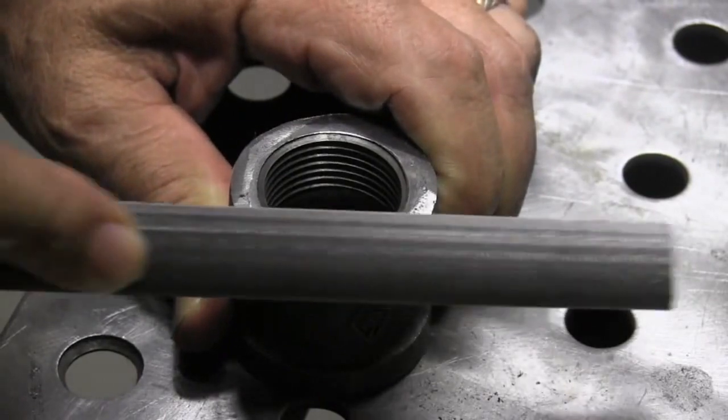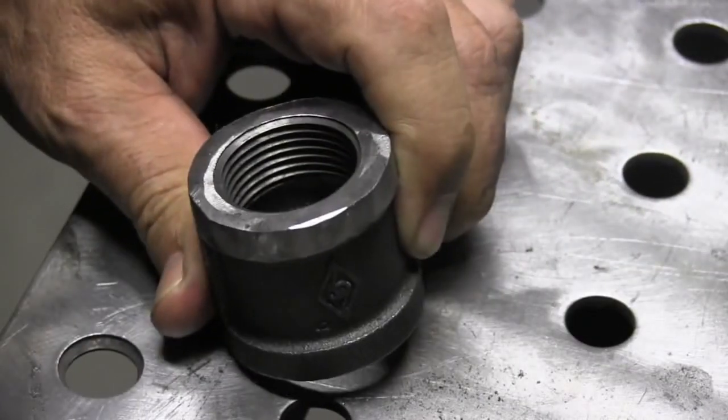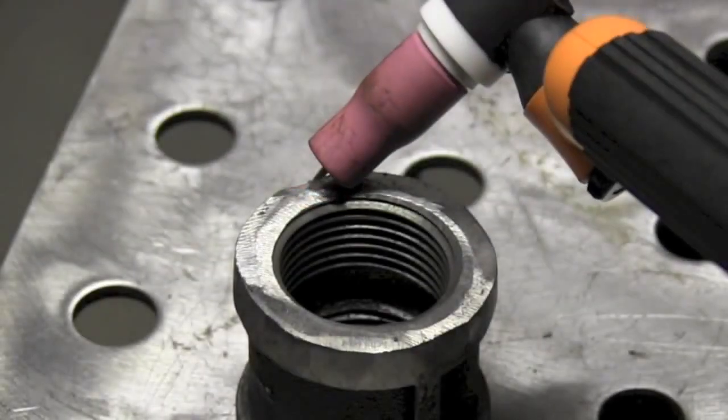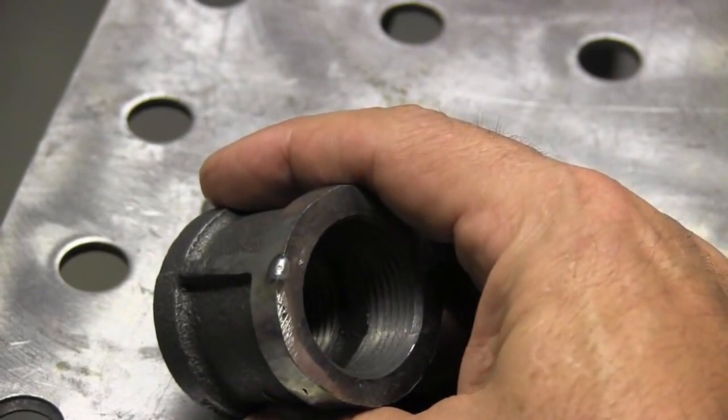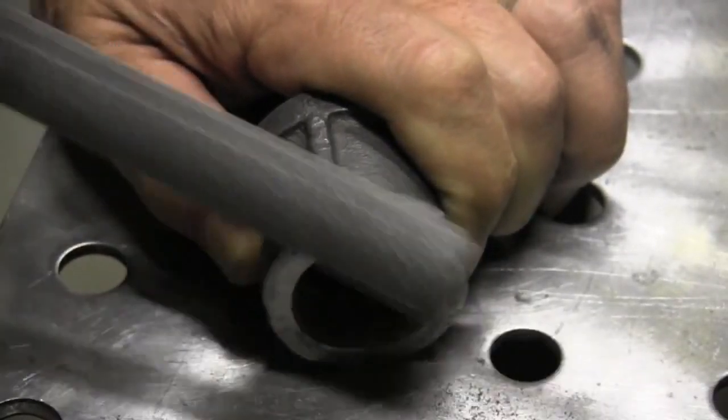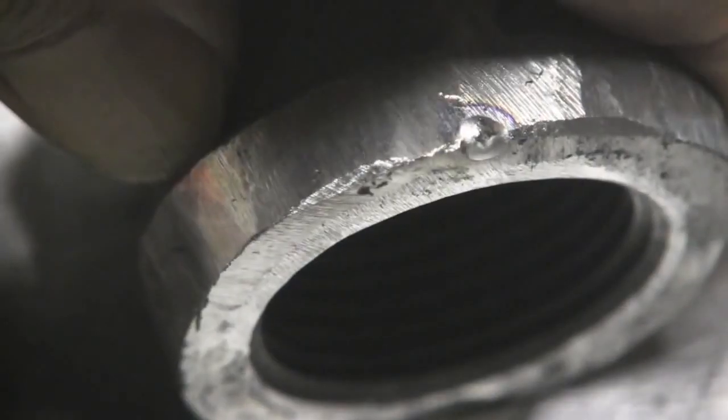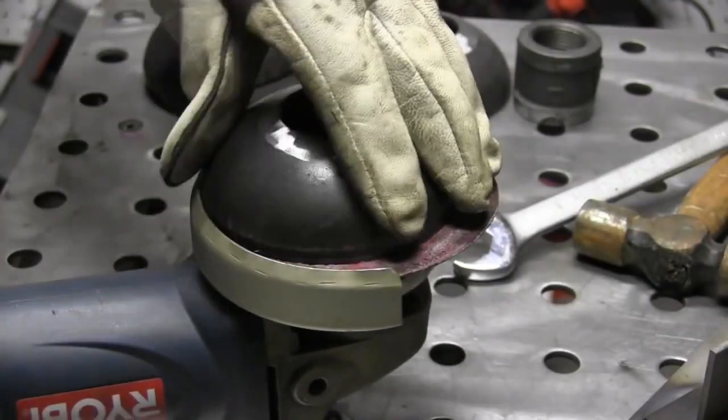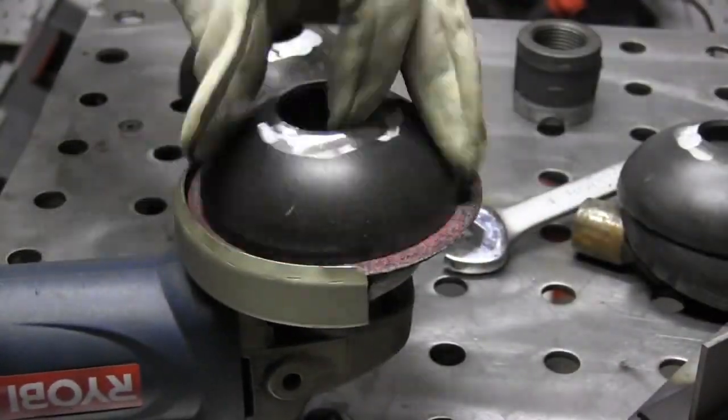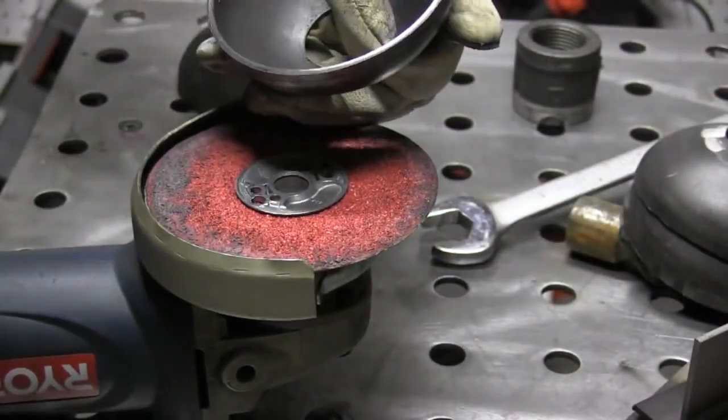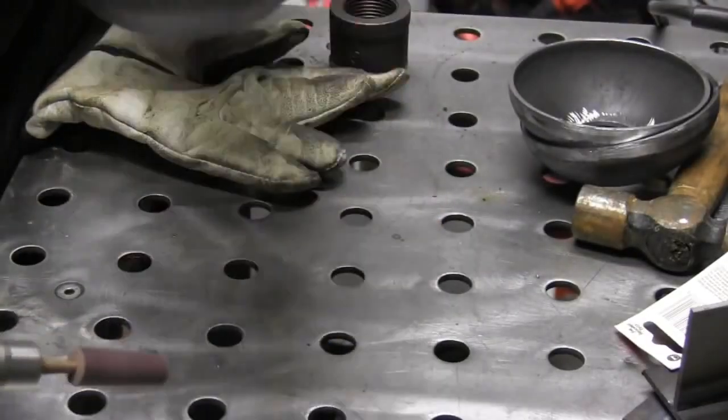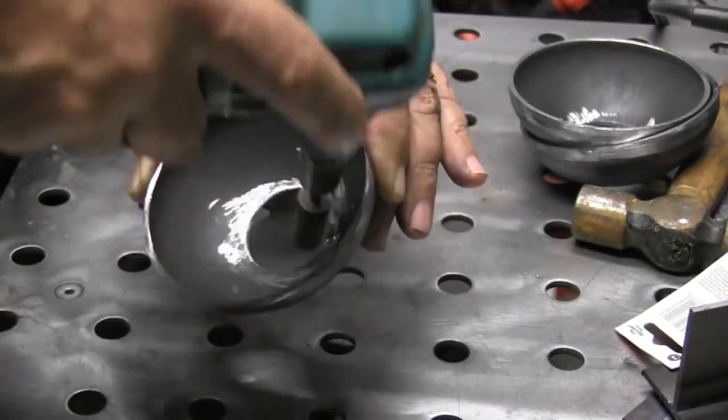Now there are a lot of different kinds of threaded fittings there's cast iron there's malleable iron there's forged steel and I wasn't able to really track down what this was by the numbering on it came from Home Depot one of them and out of the pack said China the other one said Indonesia so I'm not gonna have a lot of confidence that there's a lot of consistency on their suppliers so did the same thing here and filing that little puddled area yielded the same thing as if it was cast iron I believe this is malleable iron but still got a lot of carbon content and it wouldn't even scratch the little puddled area so I know that it's going to be hard and brittle and I'm going to probably weld it with silicon bronze could have just done that going in but that wouldn't give us a lot to talk about would it so I'm cleaning these up they're stamped apparently out of a hot rolled they got a mill scale on them so I'm getting them all clean to shiny bright metal for TIG welding here and we're just deburring a little bit there too I don't want any little kids sticking a finger in there and cutting their finger.